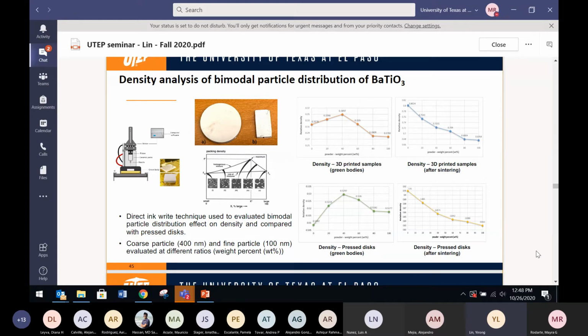As you see, the orange here shows you where you have two different particle sizes. When you mix them, the highest density is roughly 0.35, right? When you mix big with small particles. However, after sintering, let's show the blue over here, top right. The small particle, in this case 100 nanometer, gives you better density. That's because of the high surface area it has, high surface energy during sintering. So therefore, it really depends on what you want to do, right?